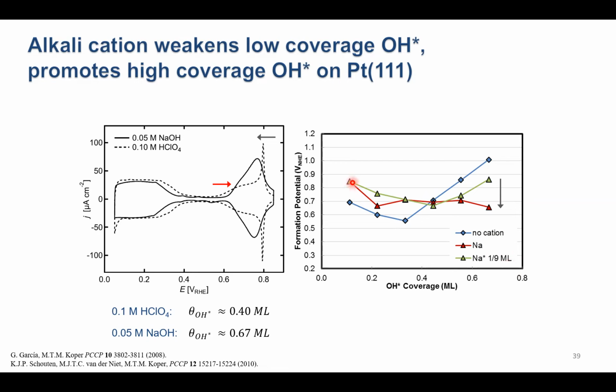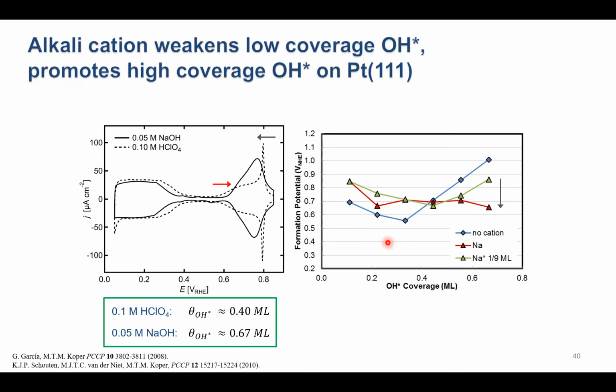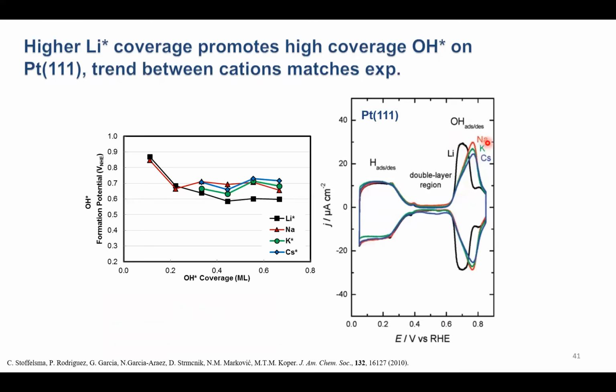So this red line now considers the most stable sodium coverage adsorbed on the surface. At high OH coverages, we get a mutual attraction between high coverage OH and the sodium cation close to the surface, which allows us to achieve a higher sodium coverage, which explains this even more significant promotion. Again, the general trend matches very well with experiment and can explain why we see an increased coverage of hydroxide in the alkaline electrolyte relative to the acid electrolyte. Again, this peak shifts because the cation weakens low coverage adsorption, and we increase the coverage because the cation also promotes high coverage adsorption.